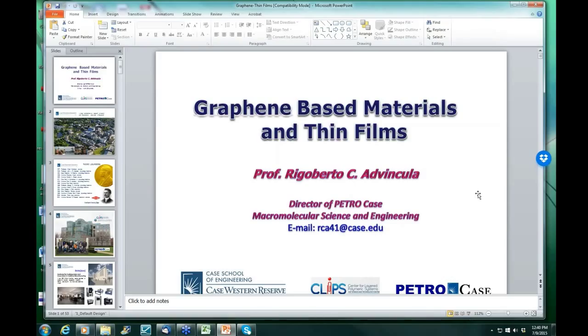So what you have there, first of all, is a difference in aspect ratio and orientation. Graphene are platelets, whereas your carbon nanotubes are fibers or cylinders. That means the percolation threshold of any particular property can either be reached through networking in the form of the carbon nanotubes, and in the case of graphene oxide, it may be a function of layering. In this case, the carbon nanotube can be dispersed as a composite material.